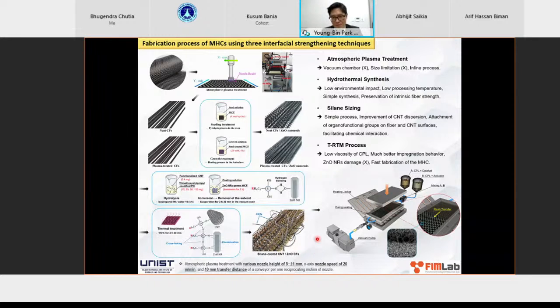So we take this fully functionalized, fully treated carbon fiber and place it in a mold like here. This is a very unique method that we created, but I'm not going to go into great detail. Here we have the monomer, the catalyst and the activator, and the resin, all mixed together. Then it is forced into the mold using vacuum. This is called vacuum-assisted resin transfer molding, but it's a very unique process because we're trying to infuse a thermoplastic instead of a thermoset resin.